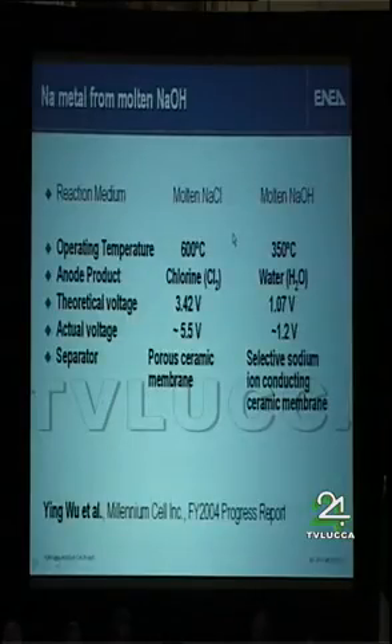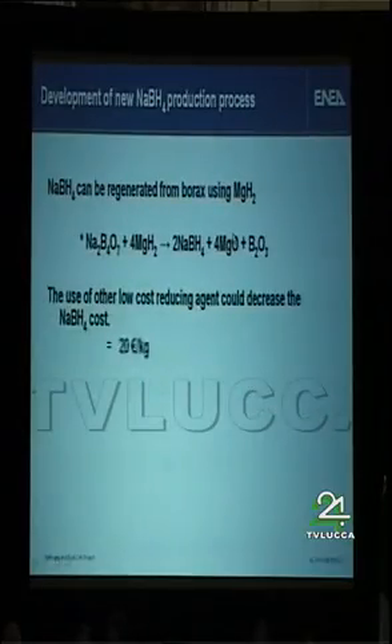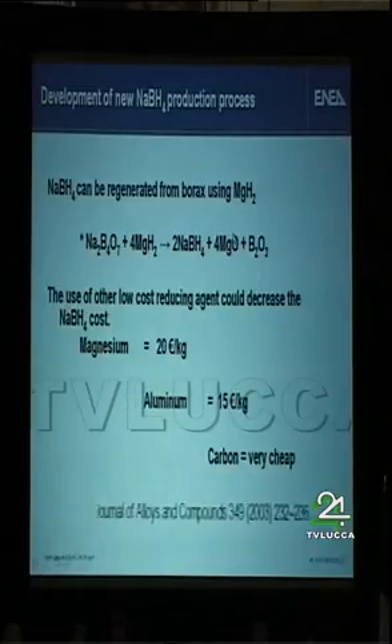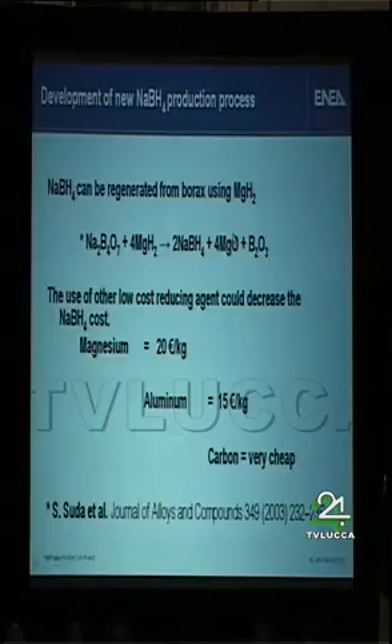So how to decrease the cost of sodium borohydride? We saw two ways just this morning. The synthesis of sodium metal starting from molten sodium hydroxide can reduce the cost of sodium. Or otherwise, we saw this morning the work of Professor Suda and others: sodium borohydride can be regenerated from borax using magnesium or other less expensive compounds like aluminum or at least carbon, which could be the ultimate way to obtain low-cost sodium borohydride. We are studying in this direction, but we have only preliminary results.